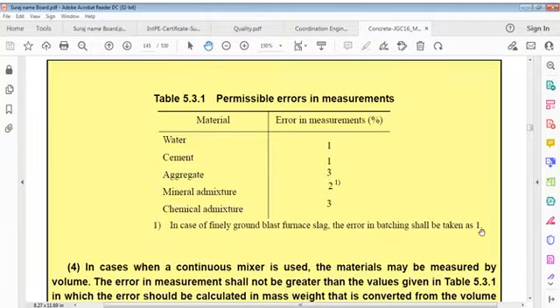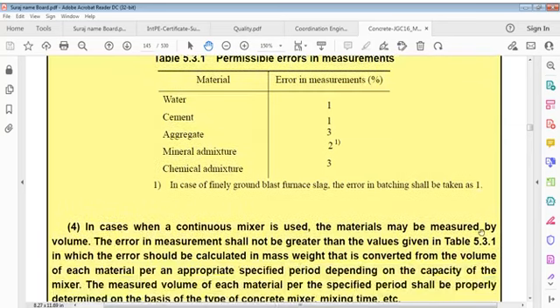Water, 1%. Error in measurement: water 1%, cement 1%, aggregate 3%, mineral admixture 2%, but in case of finely ground blast furnace slag, error in batching shall be taken as 1%. Chemical admixture 3%. So minimum is 1%, and that is water and cement. Error of only 1% is acceptable.